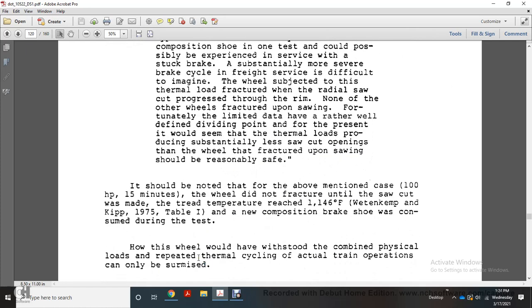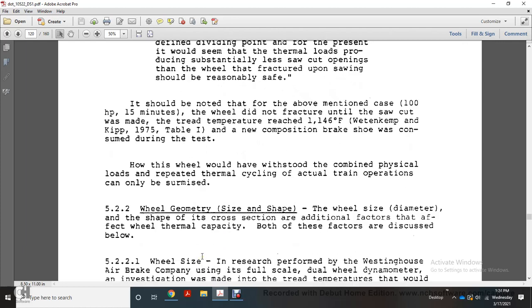reasonably safe. It should be noted that in the above-mentioned case of 100 horsepower for 15 minutes, the wheel did not fracture until the saw cut was made, with the tread temperature reaching 1146 degrees Fahrenheit, and a new composition brake shoe was consumed during the test. How this wheel would have withstood the combined physical loads and repeated thermal cycling of actual train operations can only be surmised.